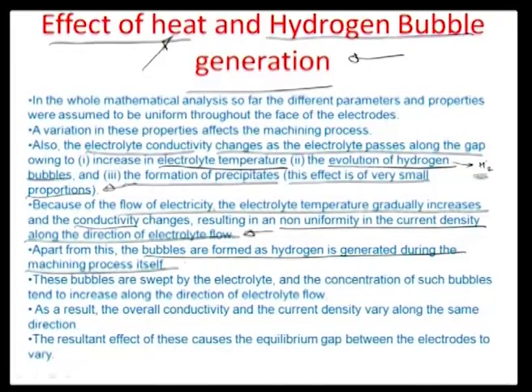So, the equilibrium gap really does not remain the same value Ye as we have predicted before. It changes quite a bit going from the entry side to the exit side of the electrolyte, and that is typically a problem in ECM systems and of huge consequence, particularly for microsystems fabrication. So, these allowances have to be taken into account when you design microsystems using ECM.